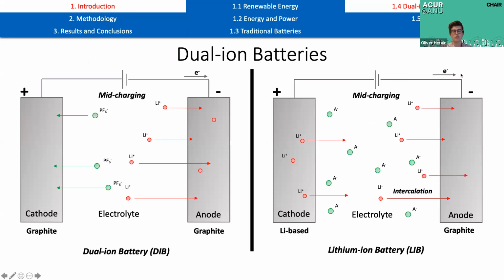So a potential solution is the dual ion battery, which is what my project is about. In a dual ion battery, the main difference is that the cathode is made of graphite rather than lithium. And most importantly, the anion is actually an active species that moves into the cathode. So it moves in the opposite direction to lithium. This shows a battery while it's charging, and when it's discharging, both ions would be moving the opposite way.